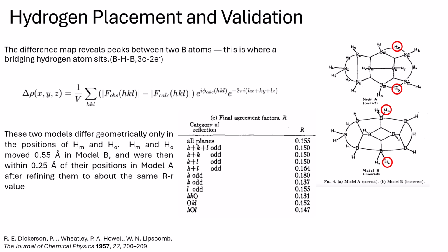So in the plot here, two different models were proposed. Model A and Model B are only geometrically different in the position of HM and HO, these two hydrogen atoms. Lipscomb used two ways to approach the validation. The first is the bond length analysis. In the correct model, the boron-boron distance ranged from 1.7 to 1.85, which is consistent with the typical boron-boron single bond, and boron-hydrogen bridging bonds are around 1.25, which aligns with the known 3C2E bond values.